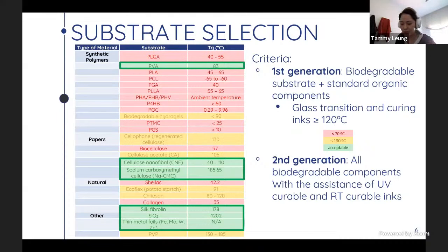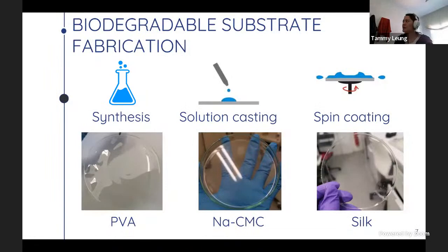When considering all of the materials here, we see that silk fibroin is sort of a standout material, as it offers the best combination in terms of the working temperature as well as biodegradability. If the substrate itself was not commercially available, we chemically synthesized it, or in terms of silk, for example, this was extracted. Because a planar substrate was necessary for the inkjet printing process, different coating techniques such as solution casting and spin coating were explored.